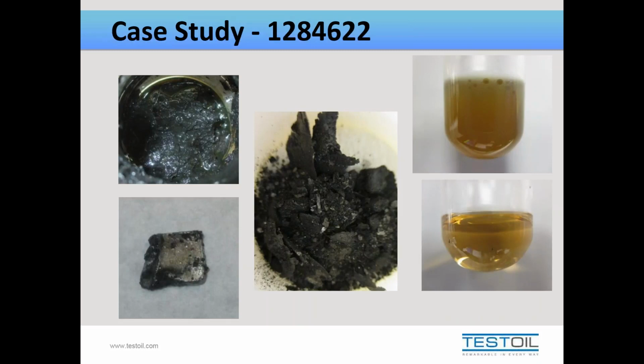Okay, so on this next one, you can see that we have a nice kind of sample of sludge here. And this sample was primarily a dark gray and black sludge that would seem to be mixed with metallic particles. This was originally sent in because a bearing within the gearbox had failed, and they suspected that there was contamination from the silicone sealant.